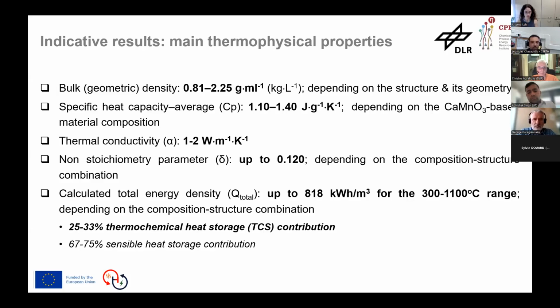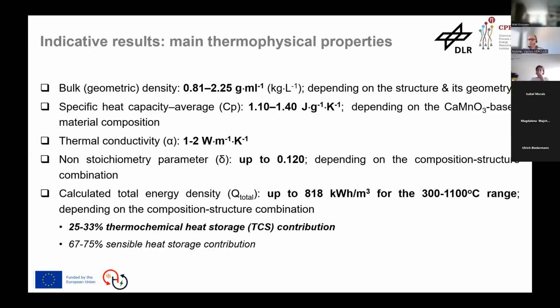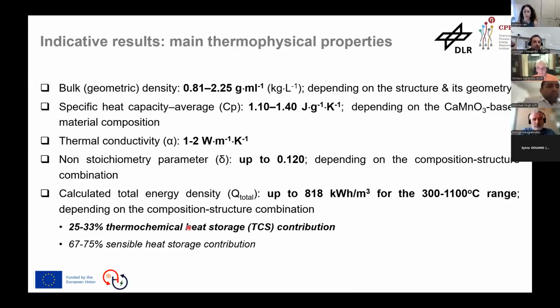And the total energy can reach up to 818 kilowatt hour per cubic meter across the range of 300 to 1100 degrees Celsius. Of this, about 1/4 to 1/3 comes from the chemical storage contribution. This shows that integrating redox active materials can significantly enhance total energy storage compared to traditional sensible heat methods.